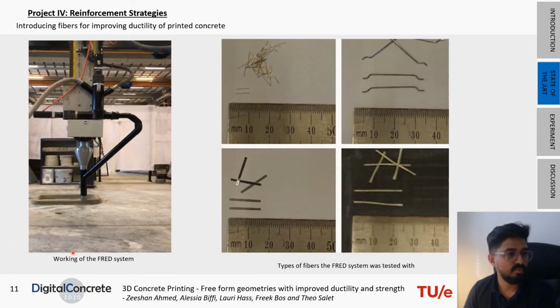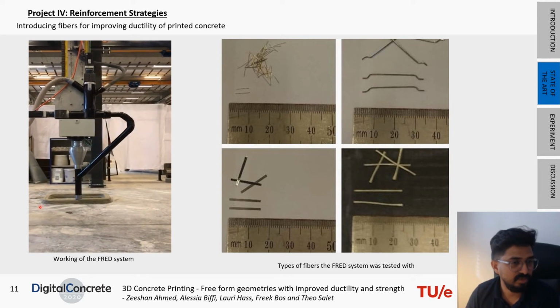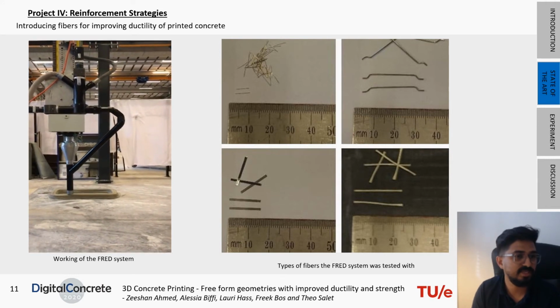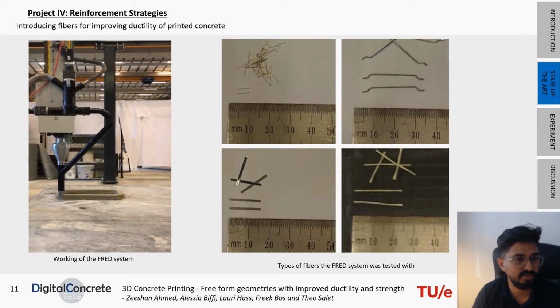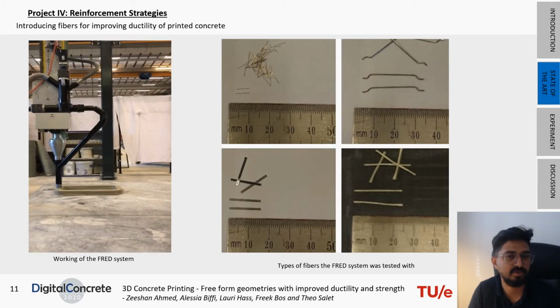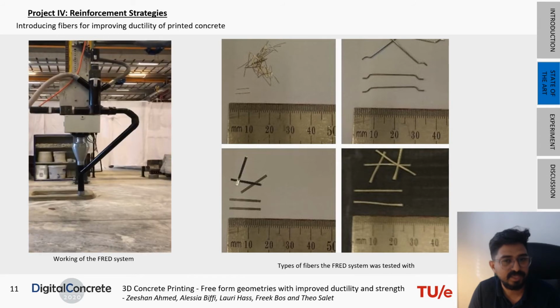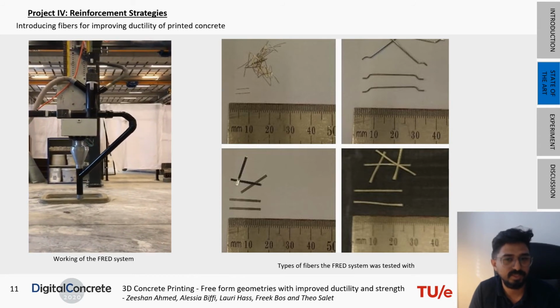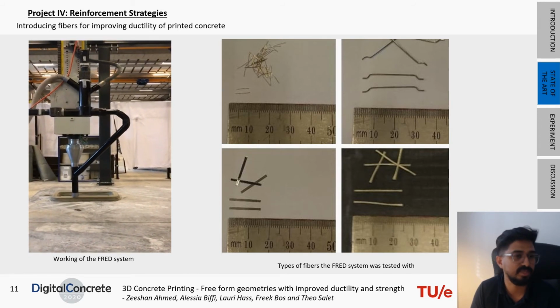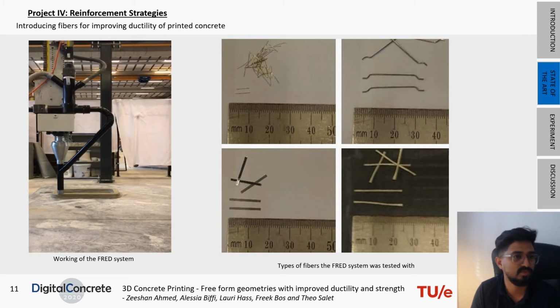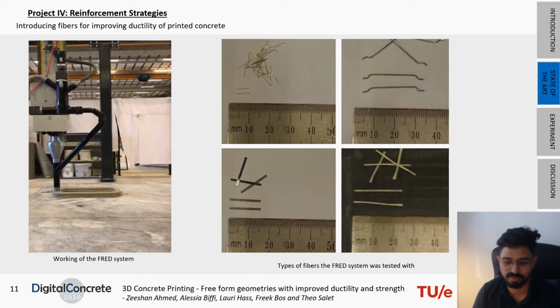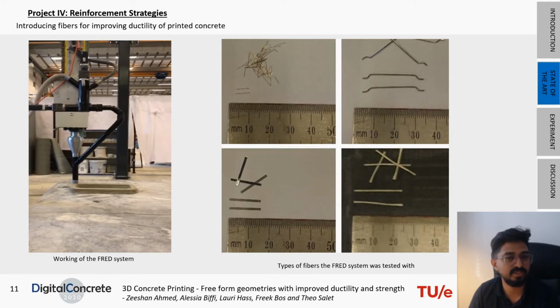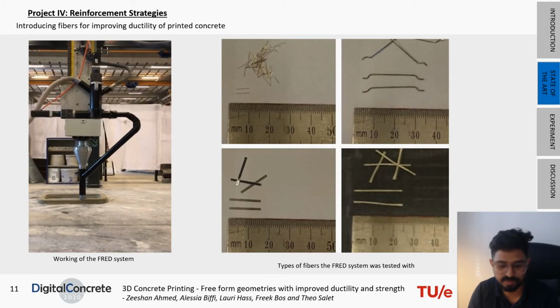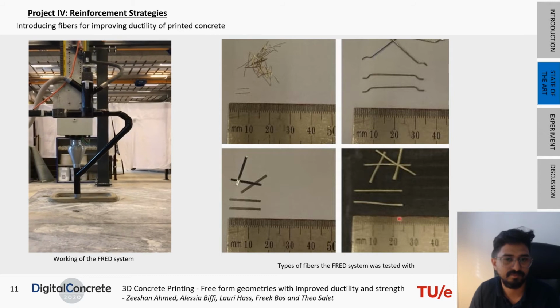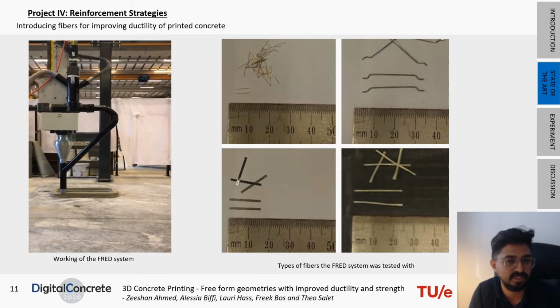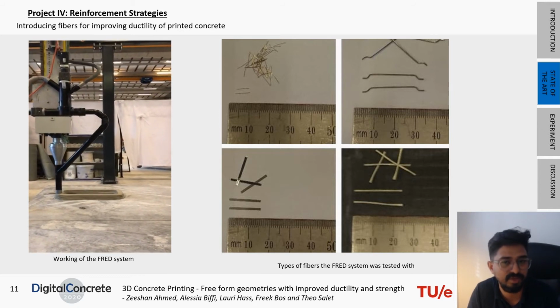To look into the working of this FRED system, as shown in the video to the left, the system was tried out with different types of fibers, both metallic and non-metallic. However, the maximum dimension for the fibers was limited to 30 millimeters, because beyond that, these longer fibers didn't work. They got clogged in the system itself. So for this research, glass fibers were used, which have a dimension of about 25 millimeters.